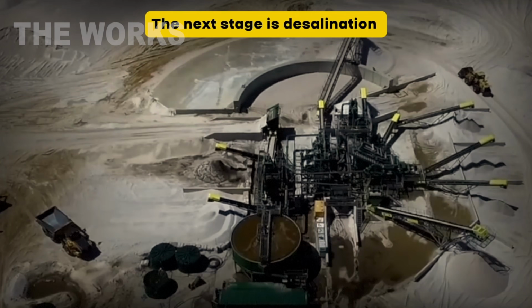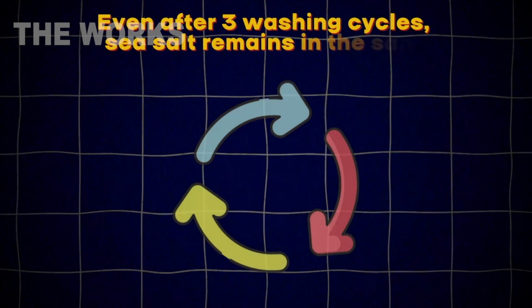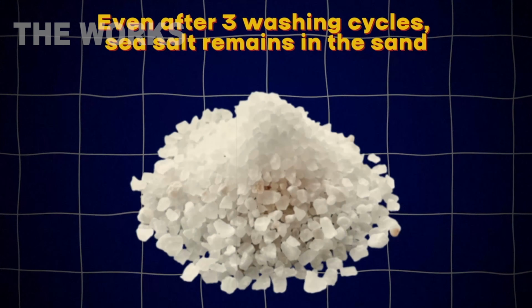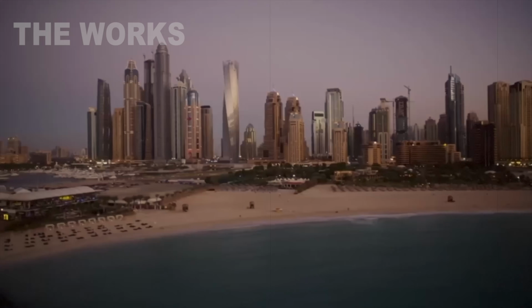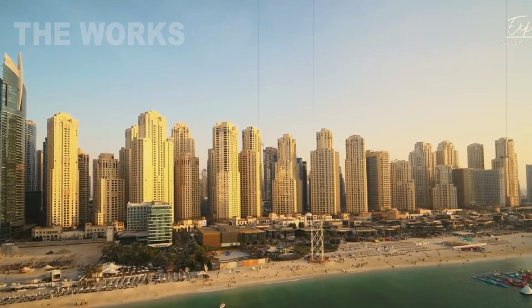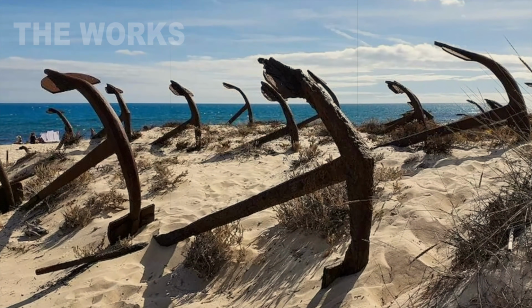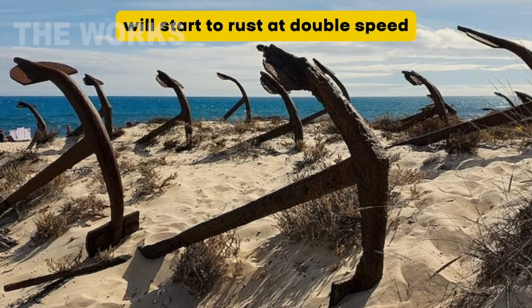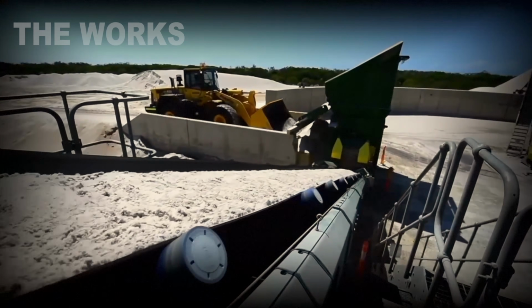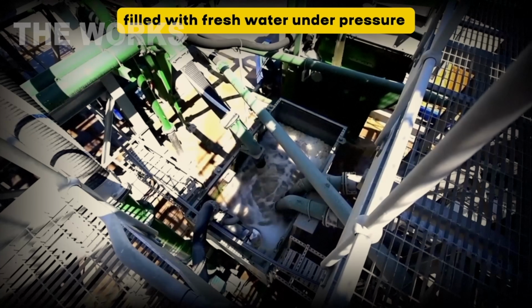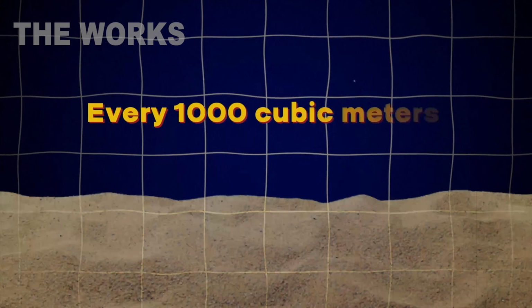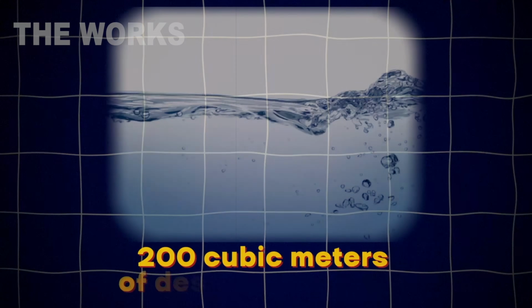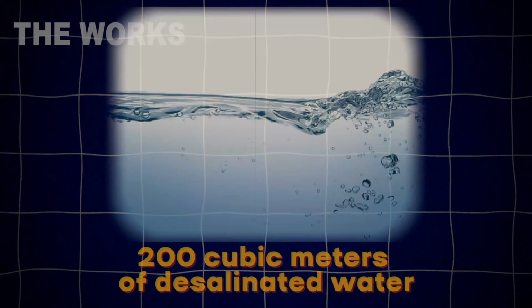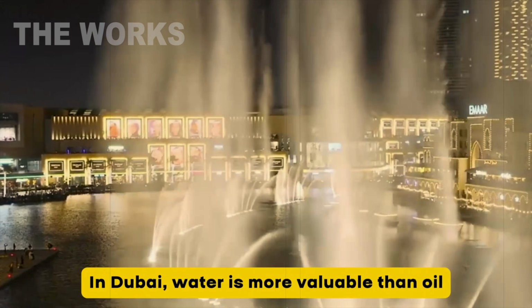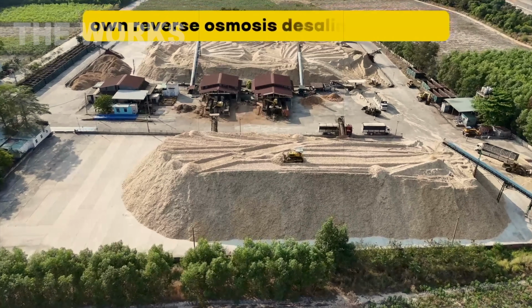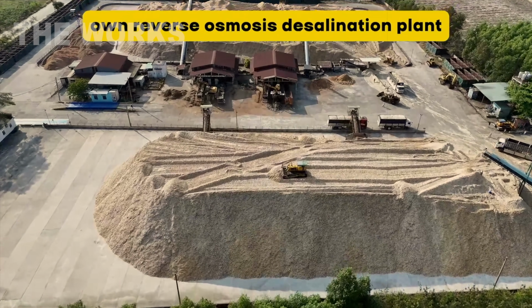The next step is desalination. Even after 3 wash cycles, sea salt remains in the sand. If you don't remove it, within a few months the beach will be covered in a white film, and any nearby metal structures will start rusting twice as fast. The sand goes into long troughs where it's flooded with pressurized fresh water. It's expensive. Every 1,000 cubic meters of sand requires 200 cubic meters of desalinated water. But in Dubai, water is valued more than oil, and the plant has its own reverse osmosis desalination unit. The process takes 4 hours.